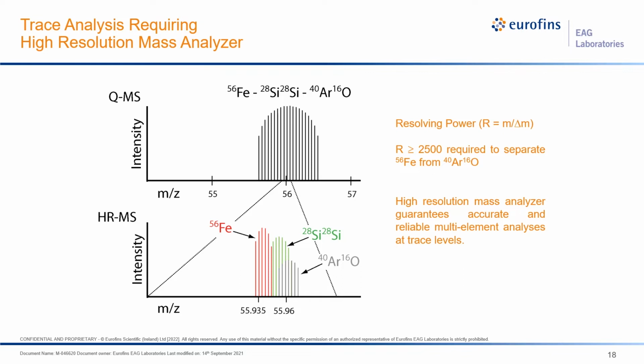Why? One of the main reasons is that the polyatomic species can form easily in the plasma. Give an example. In analyzing trace iron in silicon, two mass interferences to iron 56 happen: silicon diatom as well as argon 40 and oxygen 16. If we're using quadrupole mass spec, we don't have the resolution, and all those three are overlapping.